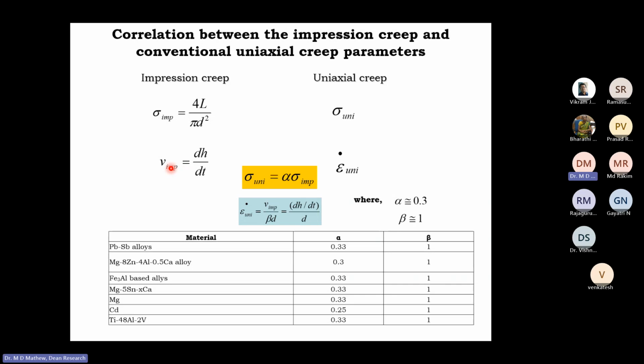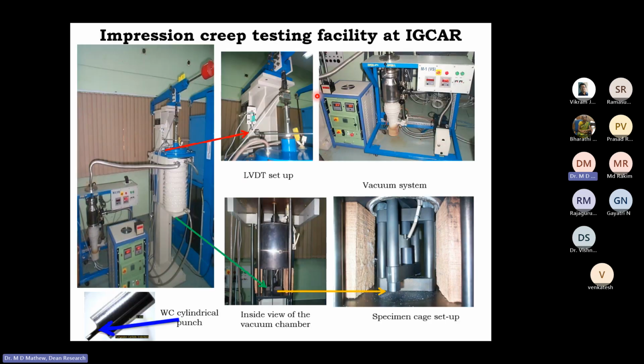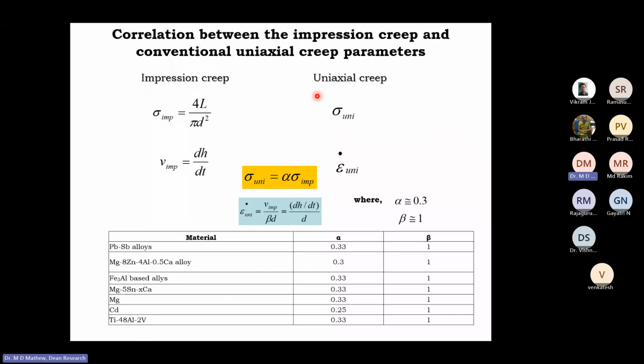Then you have the velocity of penetration, and how can we convert it to the creep rate, the strain rate? Here, the strain rate is given by the impression velocity divided by beta into d, where beta is a constant and d is the diameter of the indenter. Again, it turns out that beta is equal to 1 for a large number of materials. So we have two constants: alpha, to convert the mean pressure into uniaxial stress, and beta, to convert the impression velocity to strain rate under uniaxial tension. So now we have both sigma as well as epsilon dot. Obviously now we can correlate stress and strain rate and generate other important relationships like Norton law, etc. So this is how the impression creep data is converted to equivalent strain rate and stress data.